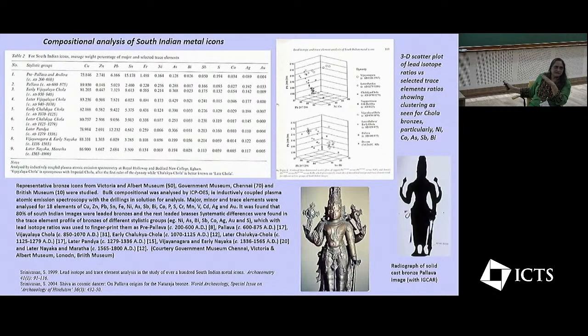Although these are copper alloys, often when you go to the stapatis, they call these bronzes panchaloha, which means five-metal icons. And nowadays, people totally mistake it to think that it is five metals or eight metals in major element proportions. But you can't actually have alloys with five to eight elements. The phase diagram won't permit you to make it. But what was actually going on here is what the Sapati explained to me, that as a Shastra, they sometimes add very small amounts, like a tola or two of gold and silver, which contributes to the auspiciousness of the image. So the fact that the gold and silver didn't show any kind of linearity or clustering like the other trace elements suggests that they were adding these minor amounts of gold and silver just as a Shastra, because that was a practice.